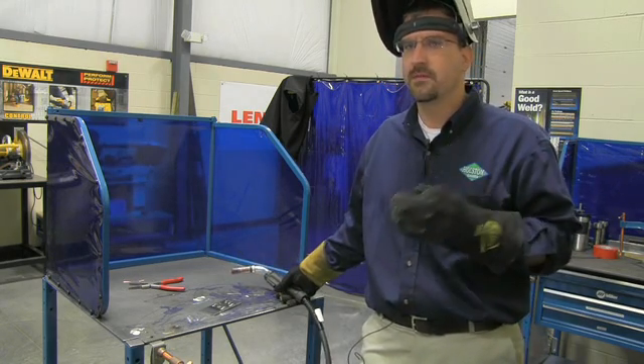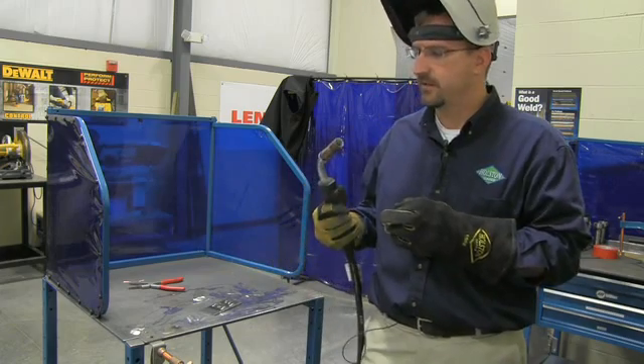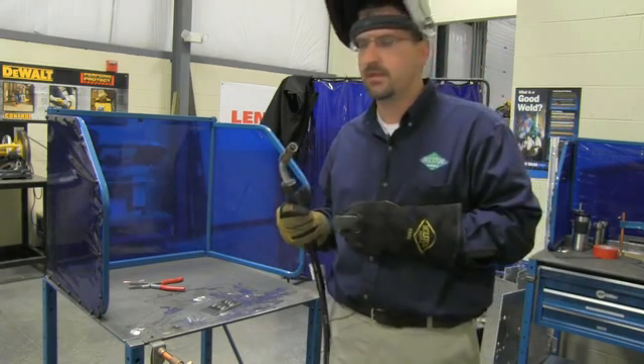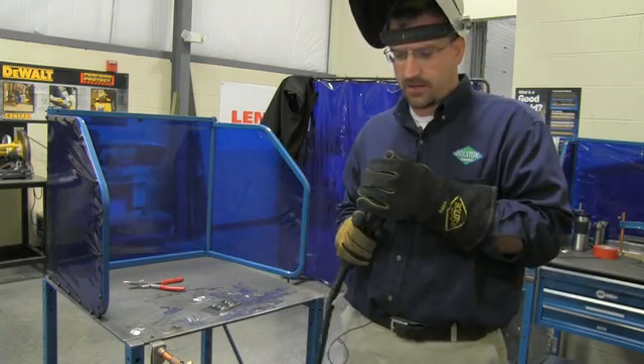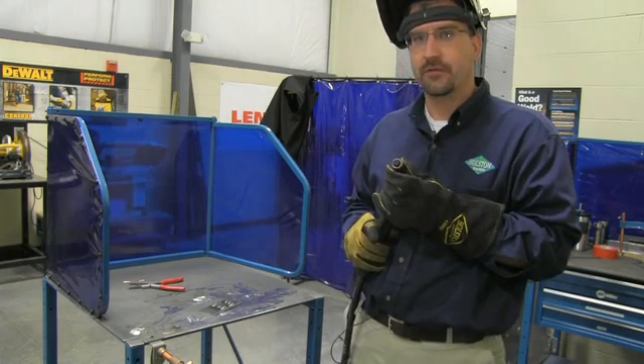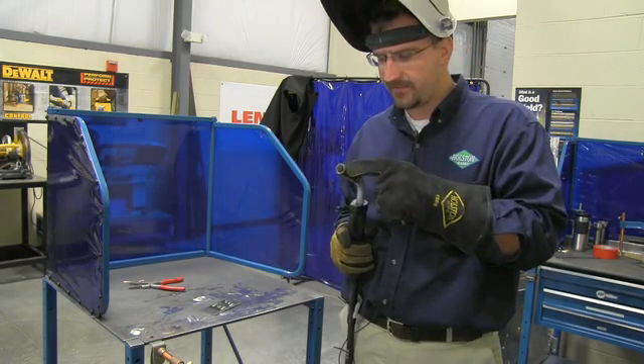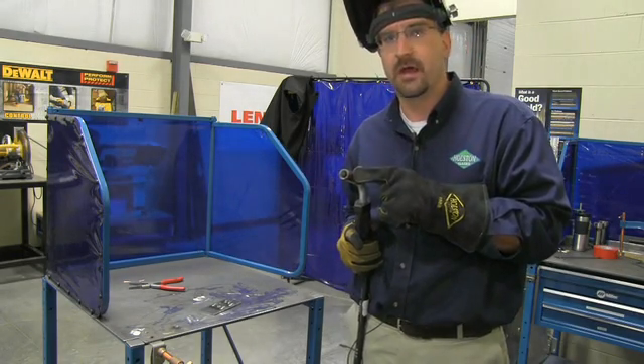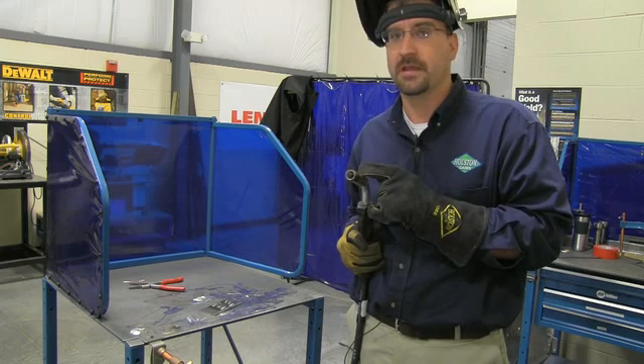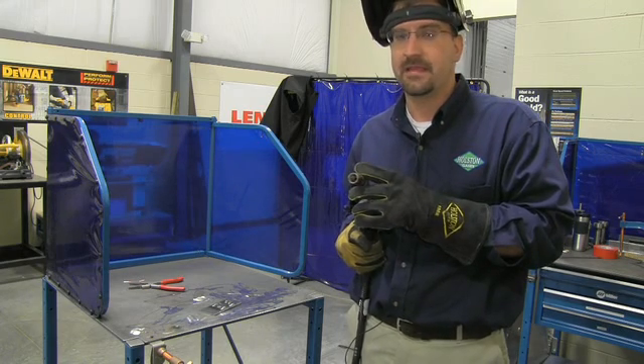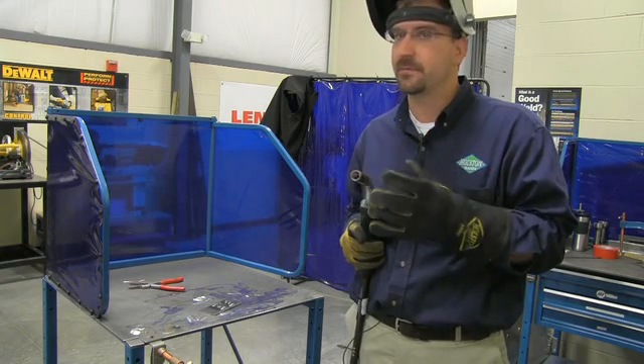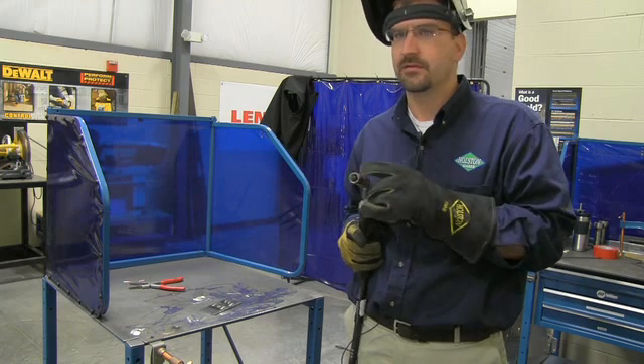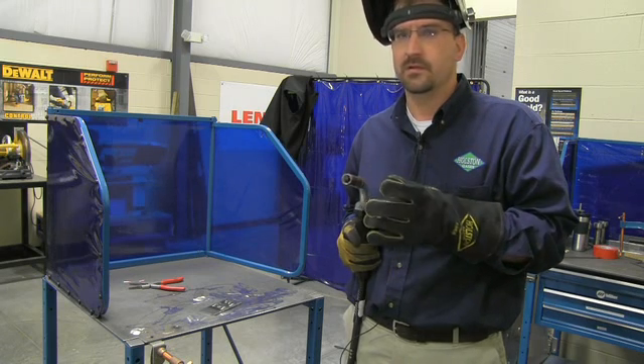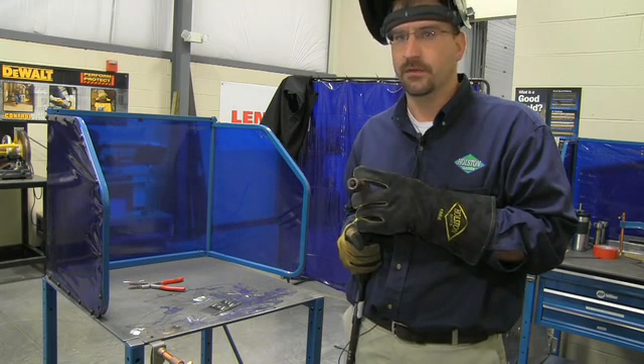And so there's really three main causes of this. The first main cause is excessive stick out. I see this more than anything. I see a contact tip that's maybe been hacksawed off so they could reuse it, and it's sucked about an inch back into the nozzle, and so they're trying to start the arc with an inch and a half stick out, and that's just not going to work. It's going to pop, pop, pop, and spatter every time, and this stubbing is going to occur, and there are going to be lots and lots of spatter at the beginning of the welds.